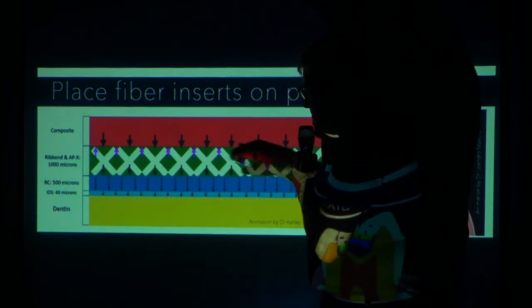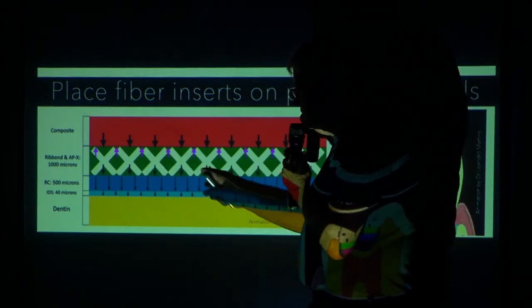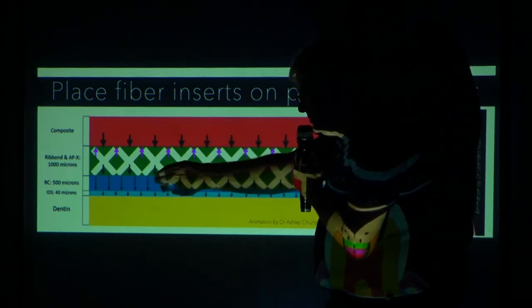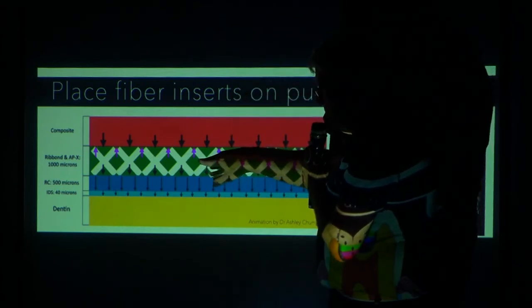Now, we get to 1 millimeter of composite. This 1 millimeter of composite, that's 1,000 microns. When we put the fiber in it, it does something very, very great. It allows the composite in these small little areas between the fibers to move in 1 of 2 directions. Half of them go up, half of them go down. The composite shrinkage of the mass on top of these bonds very strongly. These mass of the composite in this ribbon layer move towards our resin coating. If you pull this apart, it only takes about 20 megapascals to pull this apart.